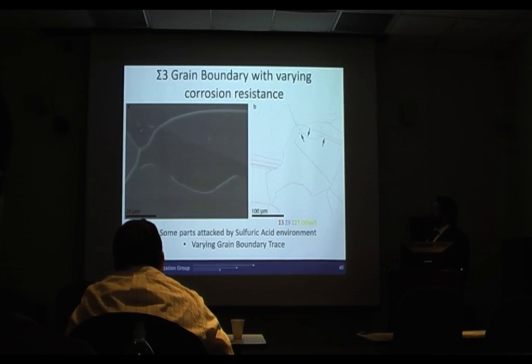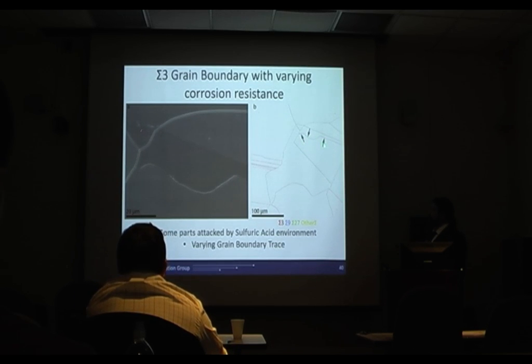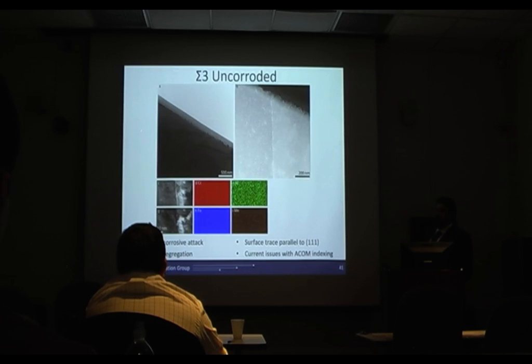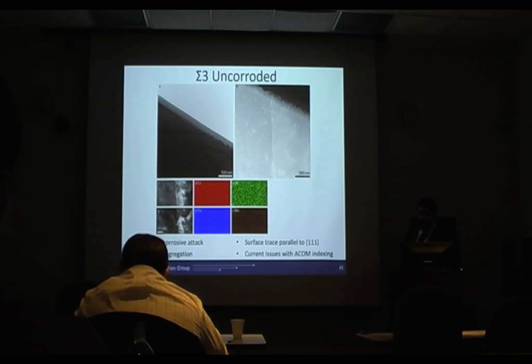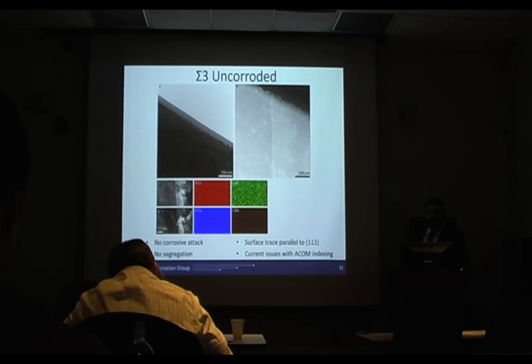So moving on, next we have the sigma 3s that I showed previously. We actually selected 3 different locations to do lift outs. The first one here is a region that didn't appear to be corroded in SEM, and in TEM we can see again that it did not corrode, and we had no segregation at this grain boundary either. The surface trace is parallel to 111, currently having some issues with the ACOM indexing of the scan, but based off Dr. Randall's methods, it's about 90% chance that it's a coherent sigma 3.